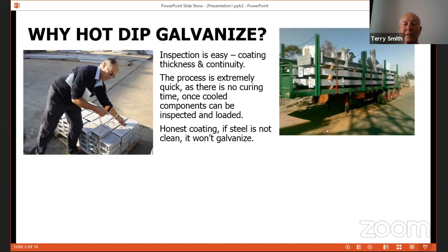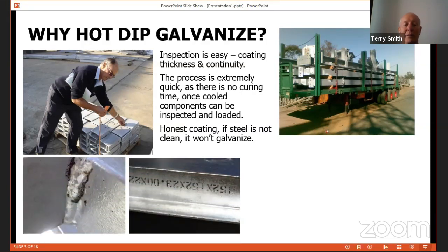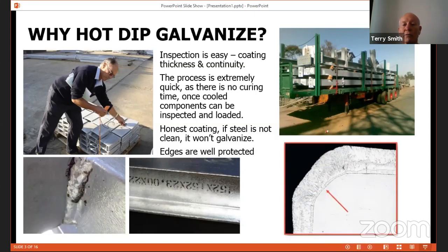If steel is not clean, it will not hot-dip galvanize. And here you can see typical examples. Weld slag, which is not removed, is shown typically after galvanizing. There's some oil-based lettering, which wasn't removed. You can see it. So the converse of that, if the steel looks good, it is good. And edges are also well protected, very different to paint, where paint thins out and would normally have to be stripe coated. Galvanizing forms equal coating around the edges.